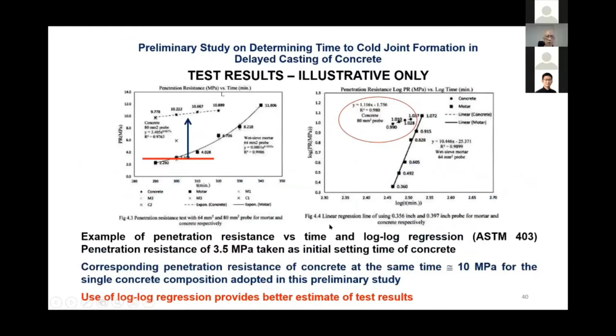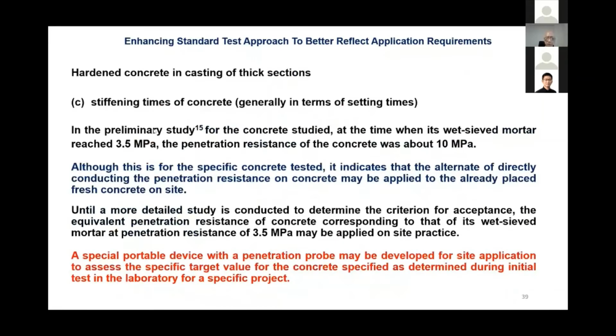Now, if you do the result by using the log curve as recommended in ASTM, then you can see when the mortar reaches 3.5 MPa, this is the time, and at that time, the wet sieve mortar reached this, the concrete reached that, and that is 10 MPa. So now, with this particular concrete, we can use 10 MPa in lieu of the 3.5 in the wet sieve mortar as the criteria for cold joint.